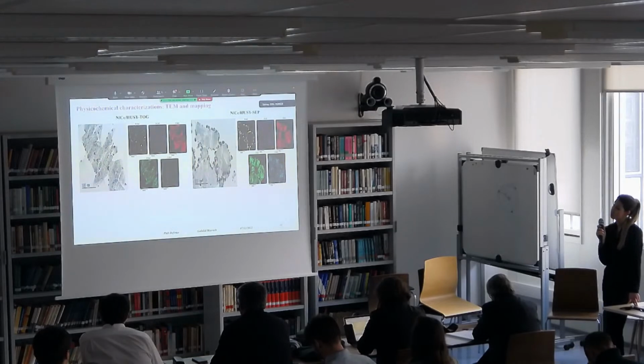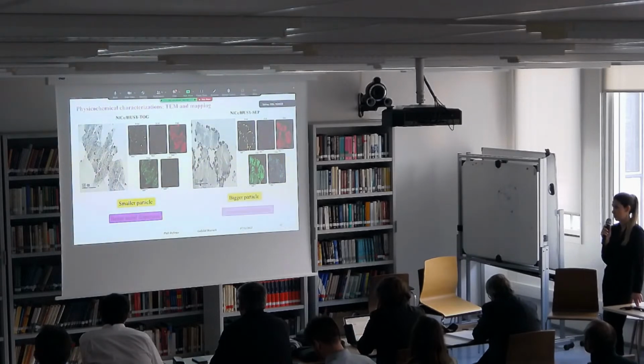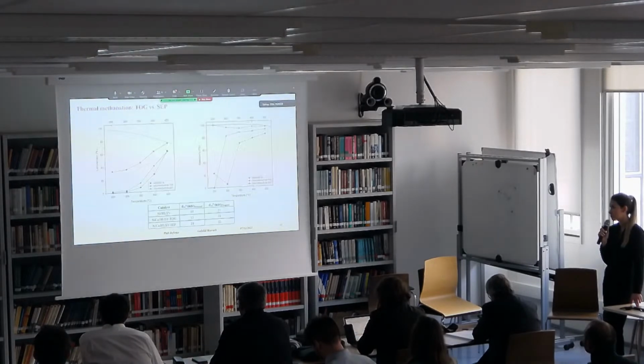Also, regarding the TEM and mapping, it shows that the TOG sample has a smaller particle size, and the particles are more dispersed on the support compared to the separated one. Regarding the thermal methanation, it can obviously be seen that the TOG sample has the best catalytic performance, not only in conversion but also in selectivity, with 78% CO2 conversion.